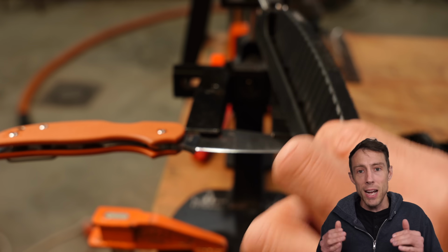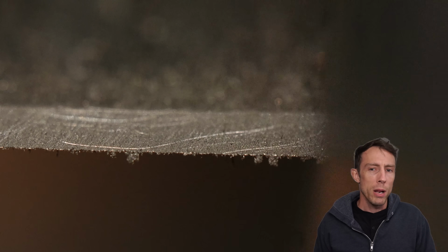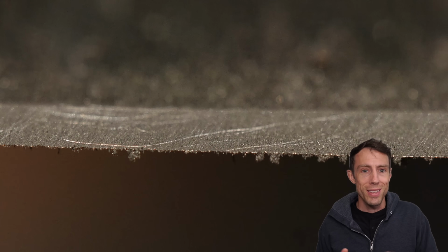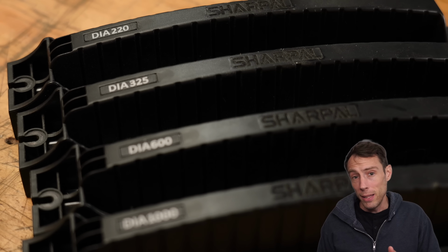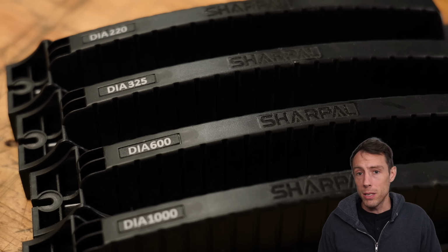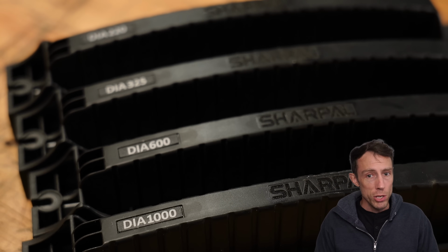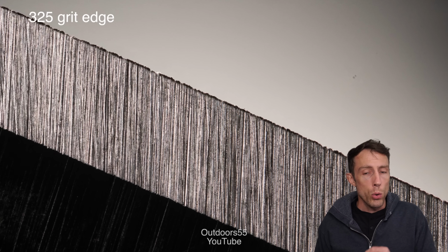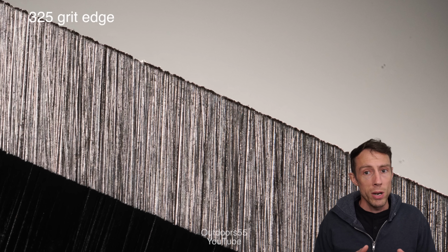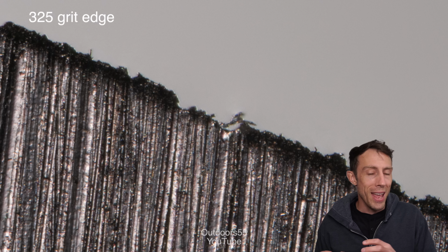Now again, we can make an entire video on the nuances of sharpening this steel, but what I found in my experimentation was that this steel works best with slightly finer grits. Now this may come as a surprise, but let me show you why. What I found was that with coarser grit apexes on Rex 121, it's very difficult to remove any burr without taking part of the apex with it.